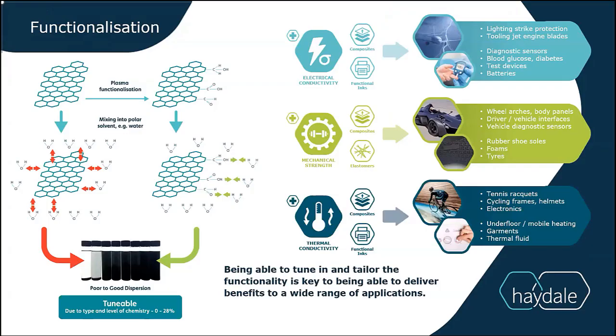Being able to provide the end-to-end solution for a vast range of applications requires tunability. By taming the chemical reactions that occur in plasma, Haydale has been able to tune in the types of chemistries and levels. This is not just by changing the feedstock of chemistry, i.e. switching out oxygen for nitrogen, but we can also select the specific chemicals required, such as primary, secondary amines, or hydroxyl or carboxyl. The infographic on the left shows how we can tailor the effective dispersion in the solvent. This is key as we target either electrical, mechanical, or thermal conductivity in an application.